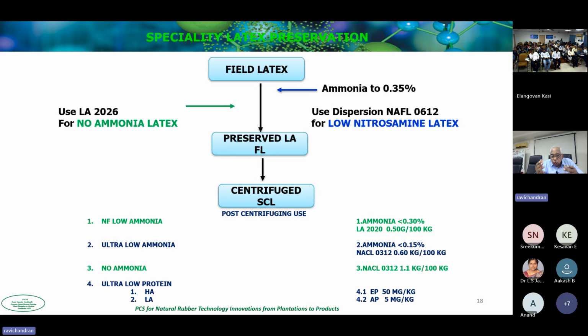These are just 2 of the new grades that we have developed and put into the market with some of our people. On the right side, you've got a low nitrosamine latex. We use a special dispersion to extract the nitrosamine out of the latex and replace TMTD, which is one of the preservatives. We've replaced it with a non-nitrosamine producing preservative.